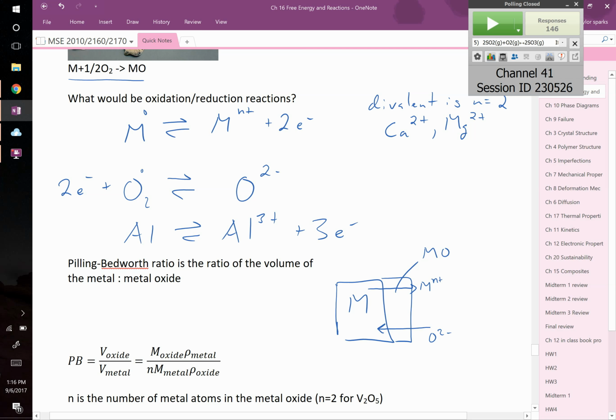So if your oxide is a really dense oxide, meaning there are no holes like Swiss cheese, a solid, coherent oxide that isn't conducive to ionic transport, which is when ions move through a solid, then your oxide doesn't grow. Because the oxygen can't get in and the metal can't get out, so it's passivated. That's the case with aluminum. Every piece of aluminum you see has a layer of aluminum oxide on it. It's very, very thin, you can't see it, but it's there and it protects the aluminum underneath.